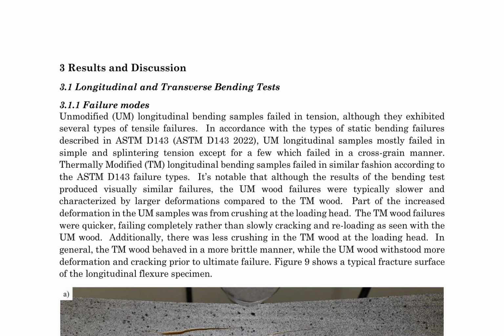The fracture surfaces of the longitudinal flexure specimens, shown in Figure 9, illustrate typical fracture paths that follow the grain of the specimen. In contrast, transverse bending samples exhibited brittle, fragile failures, with sudden and complete cleavage through the cross-section. The fracture surface was smooth, running along the grain, with no visible or audible cracking prior to ultimate failure.